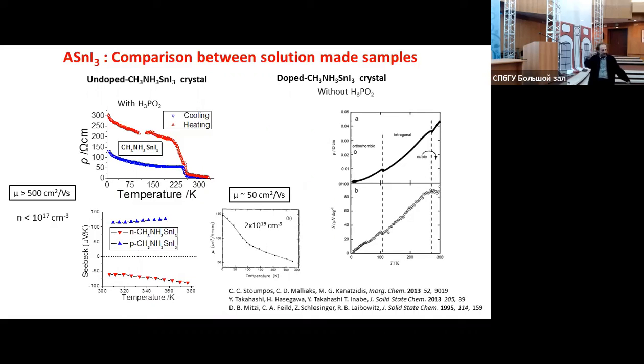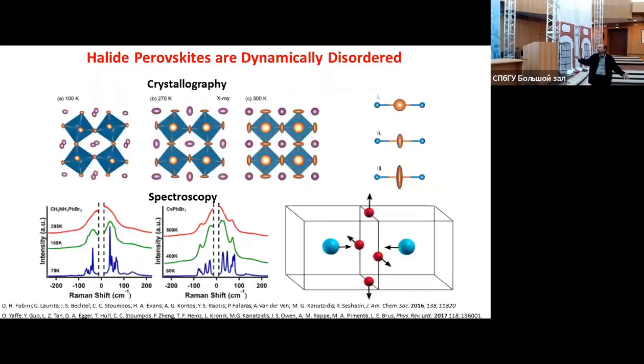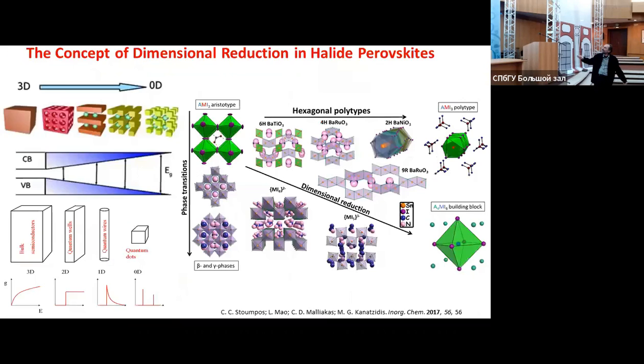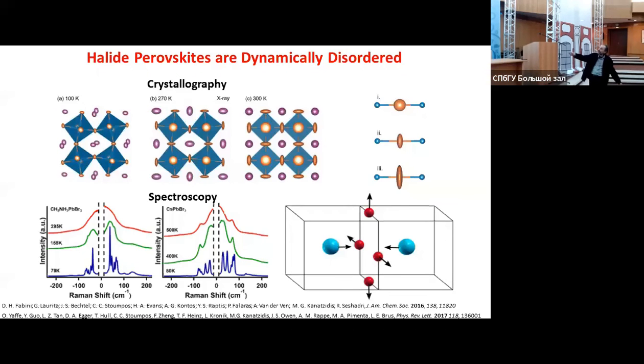And the second question is the rotation. There are actually works from the 90s that say it's on the order of megahertz rotation frequencies. They studied it by NMR. And it's also temperature dependent. As I showed you, these are dynamically disordered systems, and you have changes in the mechanism as you go from this phase to this phase to this phase. So the rotation happens thermally or by tunneling. There is a tunneling mechanism. But they studied this by solid state NMR.